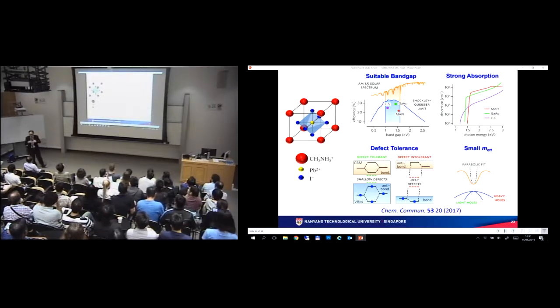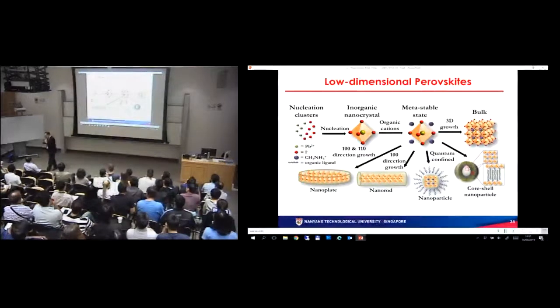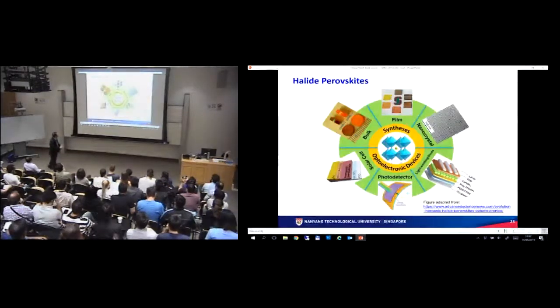Okay, so solution process works. Of course, we now know more about this. And the last property I'll mention is it has very small effective masses for both the electron and hole. As a result, your mobility is actually pretty good in this material system. And it has started to encroach into nanoscience. Using wet chemistry, you can easily play with the chemistry and then start to confine and restrict the growth in various dimensions. You get your nanoplates, your nanorods, your quantum dots, your core-shell structures, your layered structures, etc. Now, this opens up a whole new playground for many people to start studying the novel properties of this very interesting system itself. So perovskites are pervasive and very disruptive.